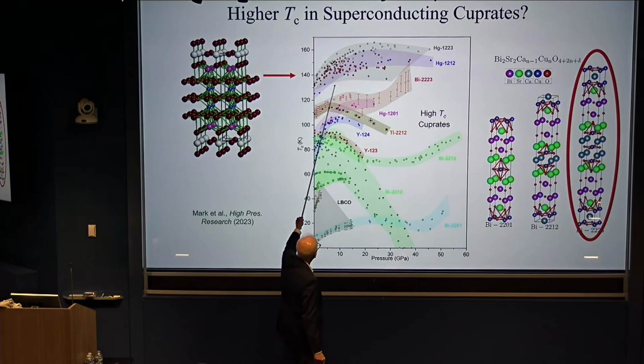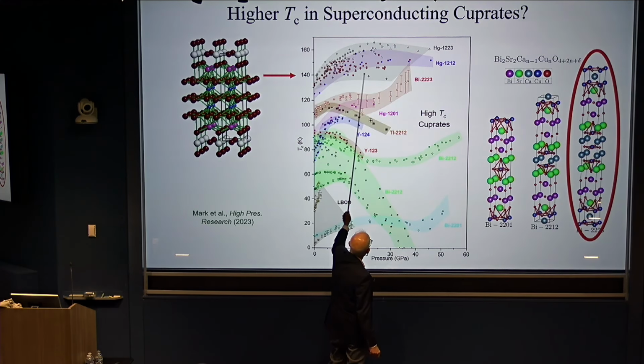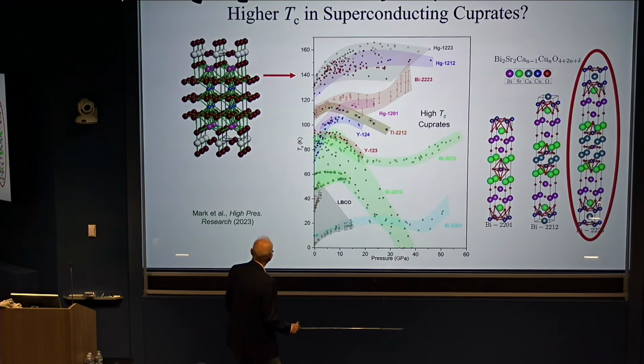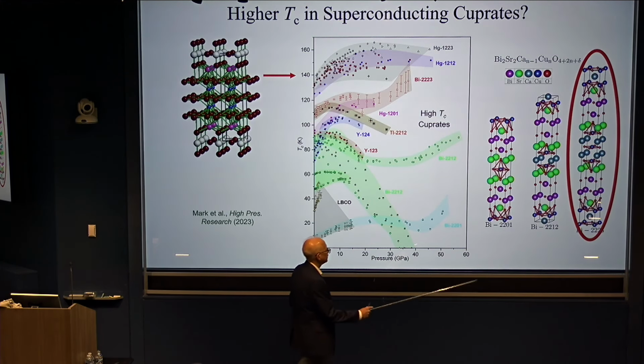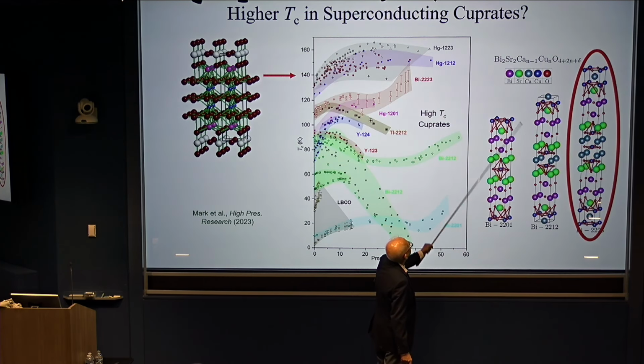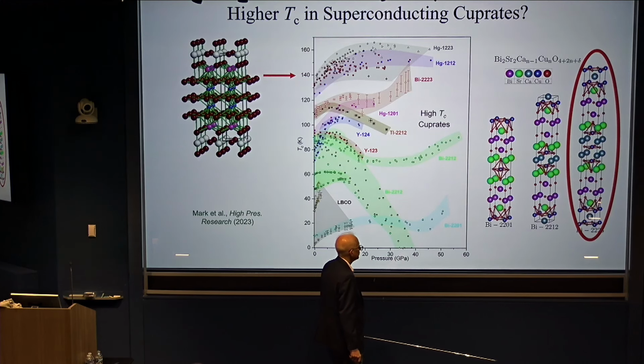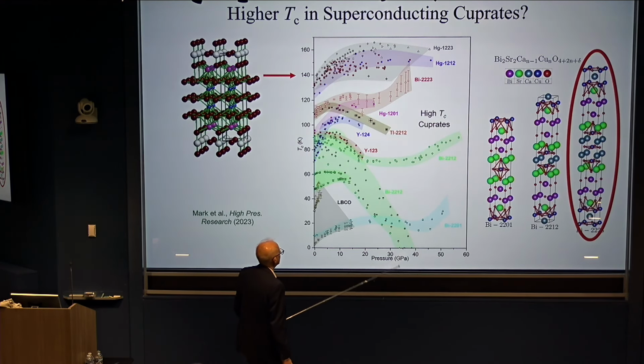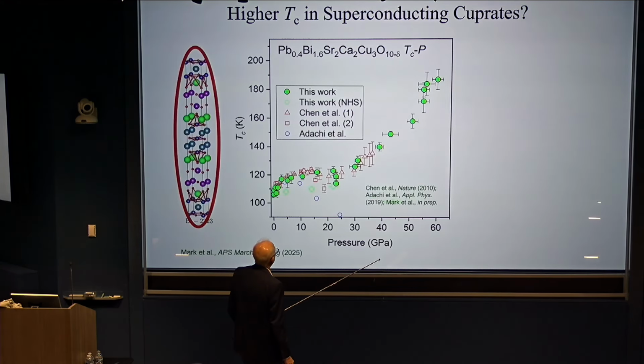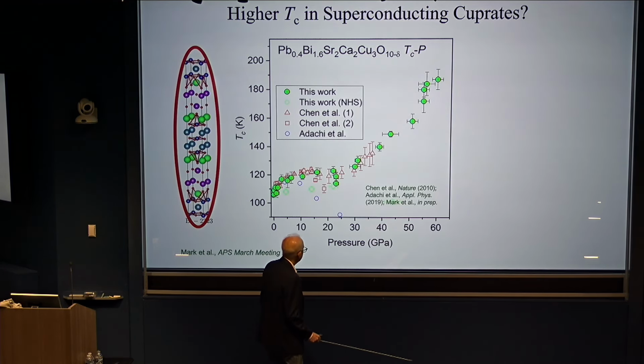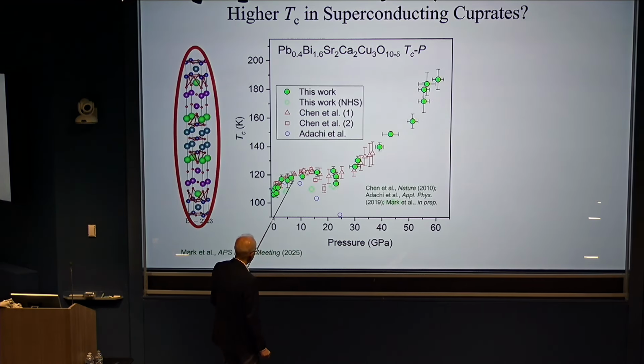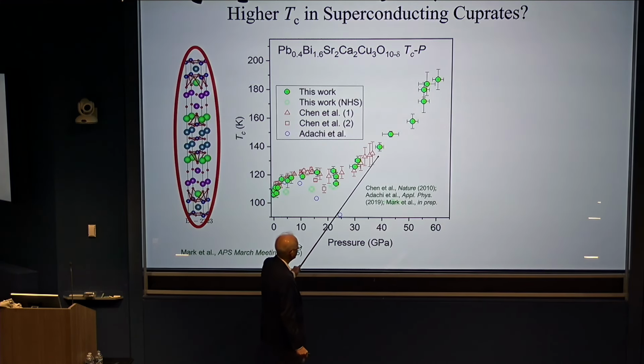This is the mercury-bearing copper cuprate here that has the highest TC. So another student, just before graduating, decided to study one of these. He looked at this bismuth strontium calcium cuprate, or BISCO, with this 2-2-2-3 structure, as it's called, and pressurized it. In work he just completed, he showed that at low pressure there's this non-monotonic behavior, but then it takes off, it keeps going.